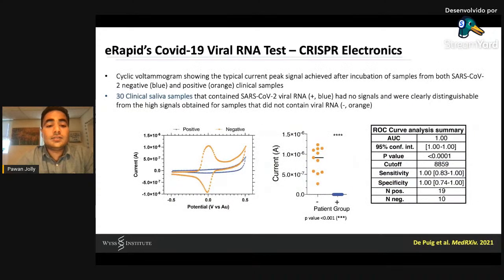So using this, you can actually see, this is what I mean. If you have a negative sample, you will see a very high signal. And if you have a positive sample, you don't see any signal. So we used this with 30 clinical saliva samples, and we were able to differentiate both the positive and the negative patient group with 100% sensitivity and specificity.